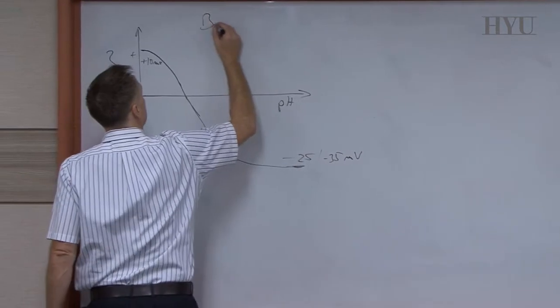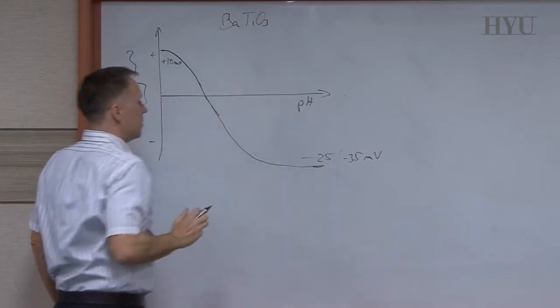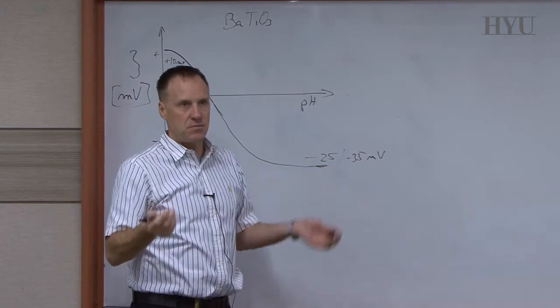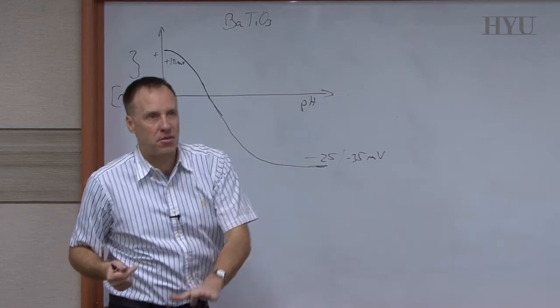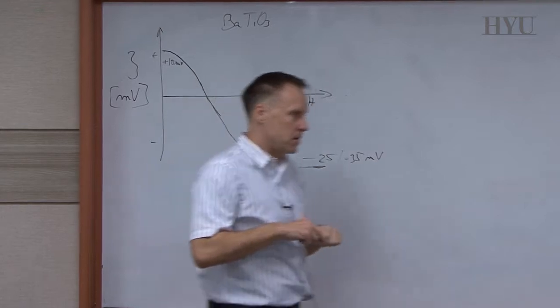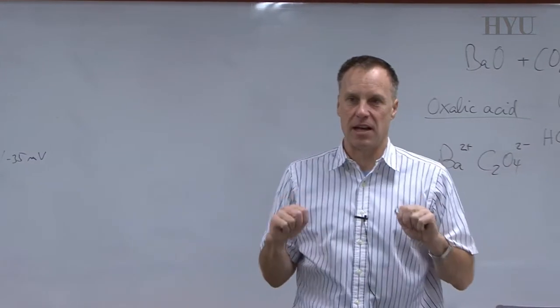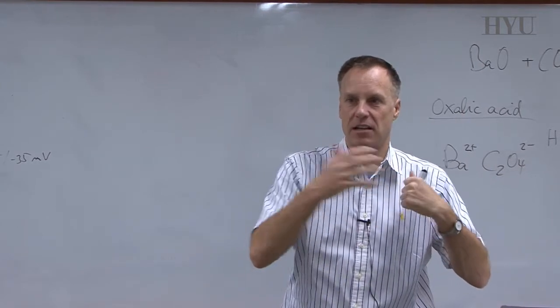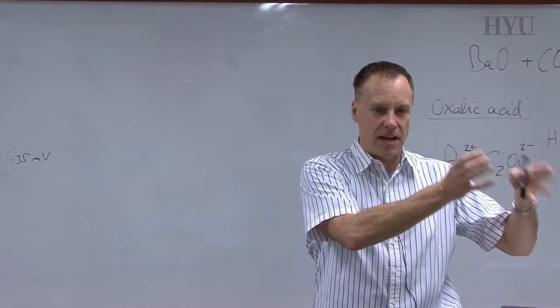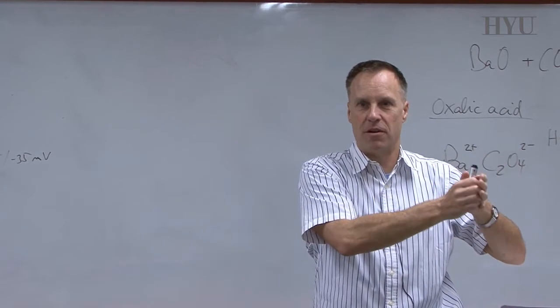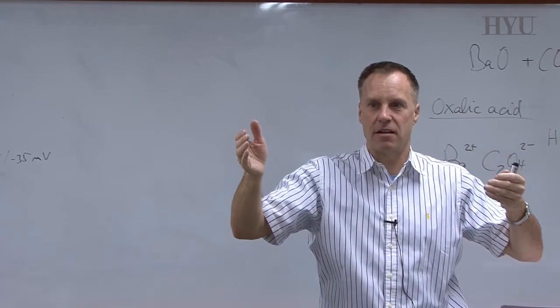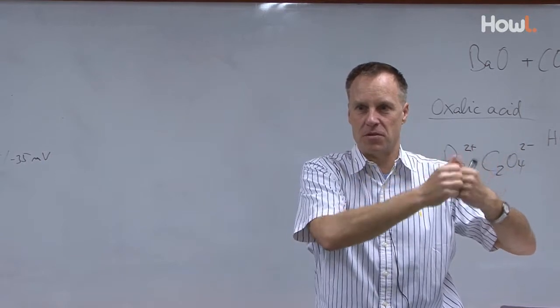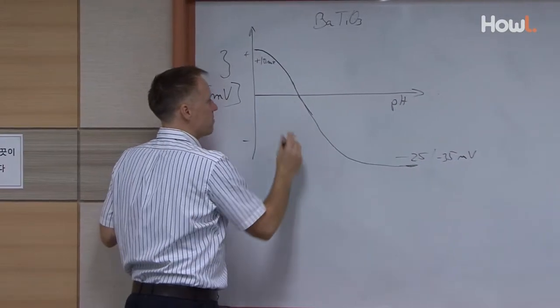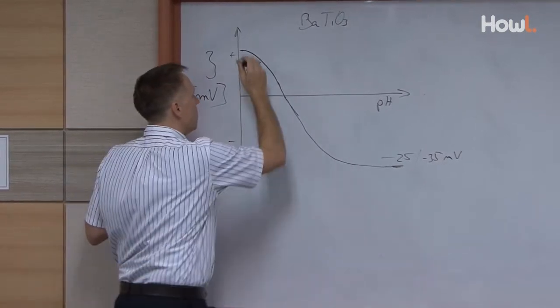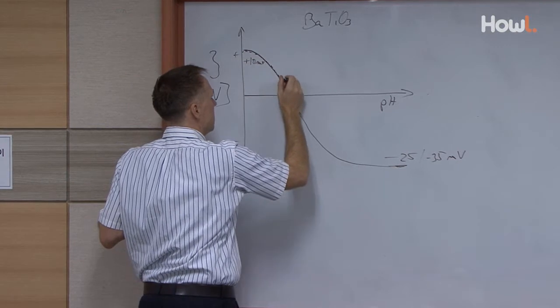Let's say barium titanate. The reason is simply that barium titanate is not stable, as we've seen. So barium leaches out, and then barium reabsorbs from solution to the surface. Because barium is a so-called potential determining ion in the system, it means it's chemically interacting with the surface. It's really weird. On the one hand, barium titanate as a phase is not stable in water, and therefore you dissolve it. The barium comes out. On the other hand, it has enough affinity to the surface that it prefers to be on the surface compared to the solution. So you get barium ions reabsorbing to the surface, and that means when you keep barium titanate in water for some time, the whole curve looks like this. It's positive, and then a little bit more like this.